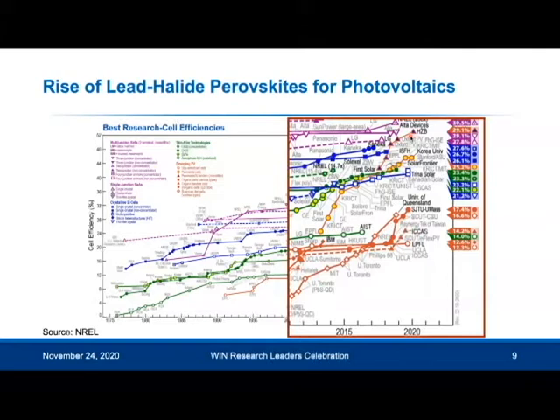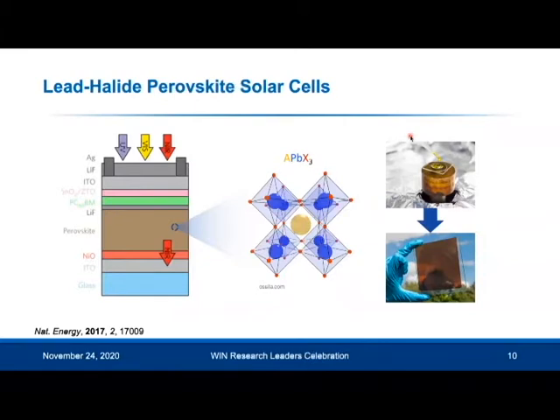So what are these perovskites? Well, when I say perovskites, I'm actually referring to a family of materials which share the same crystal structure. The structure is shown here, and these materials have 3 different components. They have an A-site cation, a monovalent cation, they have a B-site cation, and they have an anion. In this case here, our B-site cation is lead, and each lead cation is coordinated with 6 halides. This could be iodide, for example. And these lead halide octahedra share corners to form this cubic unit cell. And to hold the whole thing together, we have this monovalent A-site cation, which is the right size to fit exactly within this void. And typically, this will be an organic cation, such as methylammonium.